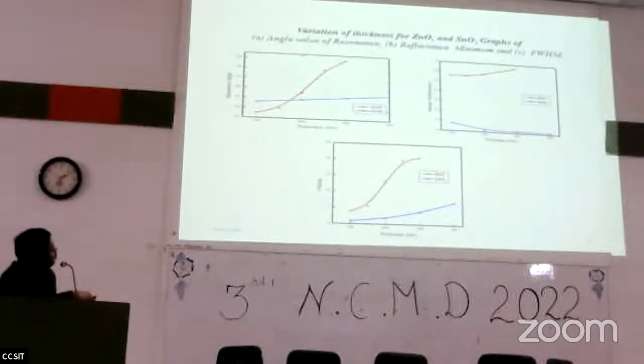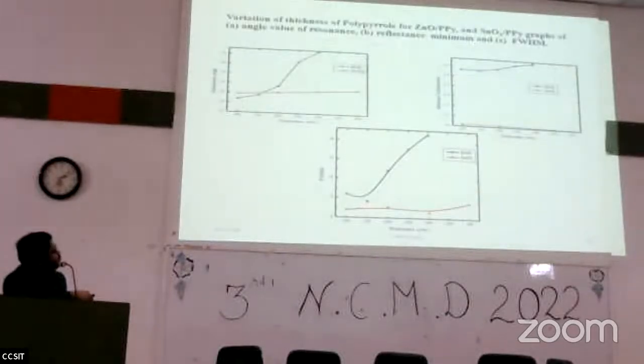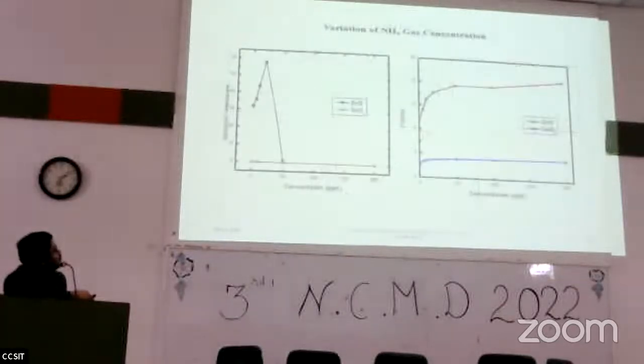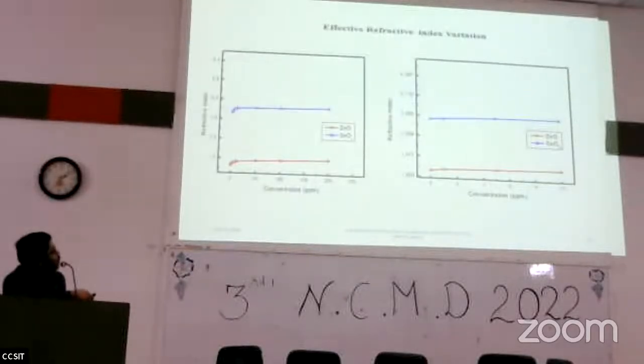So this is the resonance angle of the two, ZnO and SnO2. Then minimum reflectance and full width at half maximum. So we can see that SnO2 performs best as compared to ZnO. This is the polypyrrole variation, and this is the ammonia concentration variation. Then refractive index variation of the two sensors.